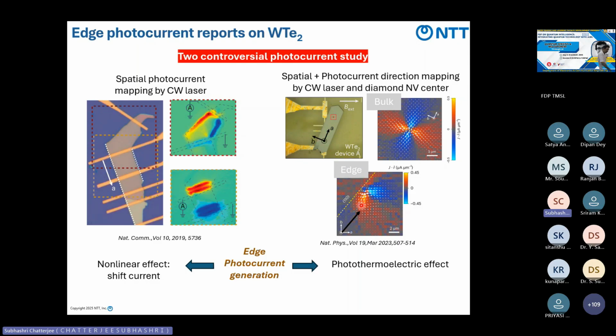That's why we cannot see any photocurrent on the bulk or higher symmetry regions. But when we shine light on a lower symmetry region, like an edge or an angle, we can have a photocurrent because there's no opposite direction current to cancel it — the symmetry is broken, so we see a photocurrent. This is simply due to temperature-gradient-induced photothermoelectric effect, not a nonlinear photocurrent effect.